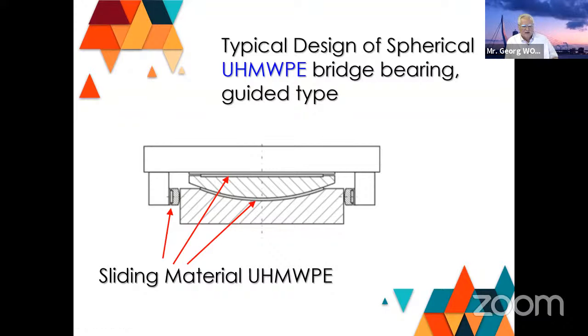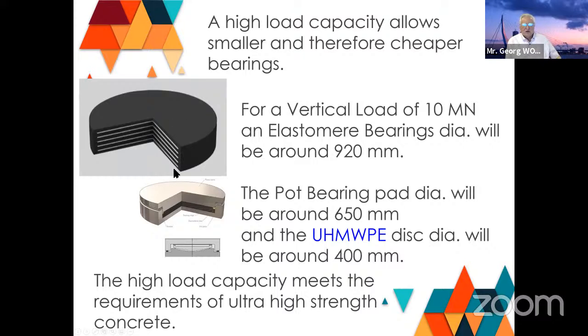So when you now compare three designs of bearings, you see the high load capacity. For a vertical load of 10 meganewton, the rubber bearing will have a diameter of around 920 millimeter. The pot bearing will be around 650, and the ultra high molecular weight polyethylene disc will have only 400 millimeter. So this also goes very well with the use of ultra high strength concrete, which is being used more and more. And of course, when the bearing is much smaller, it's also cheaper. It has a lower price.